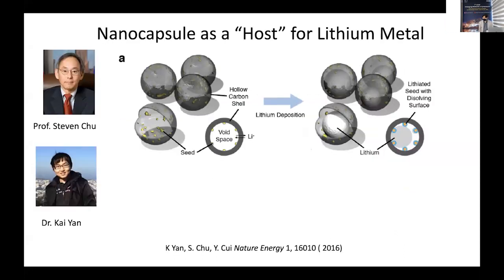So using this idea, we are building a host for the first time. It is hollow carbon. We actually screened all types of hosts. We found out lithium has a nucleation barrier on carbon, and lithium would not like to nucleate directly onto carbon. If we build a hollow carbon host and put a gold nanoparticle in the middle, once we deposit lithium, lithium ions will like to diffuse through this carbon shell and deposit inside of this hollow carbon.